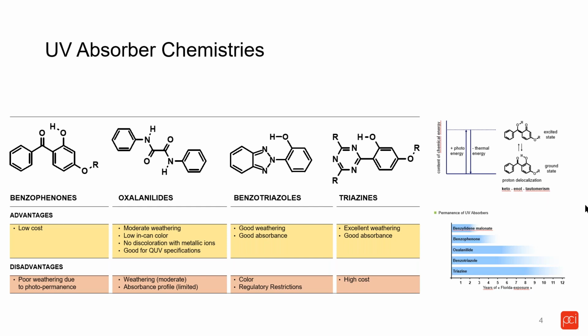So basically the triazine, which is known to have very good durability, is very likely the UVA of choice for high performance requirements. The triazine will very likely last much longer than the benzophenone or oxanilide, and even some benzotriazoles. For benzotriazoles, there are actually several chemistries, and among them there is a big differentiation between the photopermanence of the different benzotriazoles. But basically, in the coatings industry, for high performance applications, we can either seek a very highly photopermanent benzotriazole, meaning a benzotriazole that will have a long-lasting effect in the coating, or very likely also a triazine.